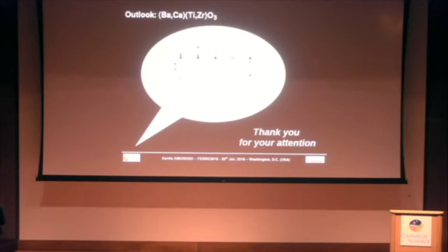Yes. I didn't show here the phonon dispersion curves because it was not related to the polarization properties that we were talking about. But it's true that at the R point of the cubic Brillouin zone, there is an antiferrodistortive instability that is quite small, actually. But in fact, some rotations are allowed to lower the energy with respect to the cubic phase. But from the experimental point of view, people are still not able to observe those structures. Okay, thanks.